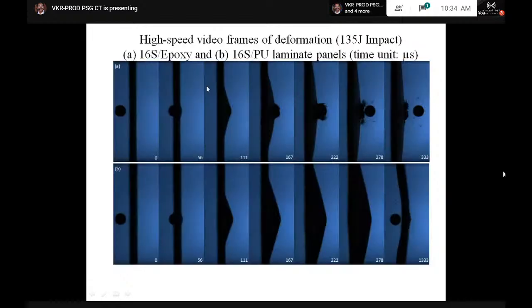This is another one where you have 16S epoxy and the 16S polyurethane laminate panel, and the brittle laminates. Of course, I can say the brittle laminate actually allows the projectile to pass through. It breaks the fibers and allows it to pass through. Whereas the ductile laminates, same grade of fabric is used here, and it actually stops the steel ball.